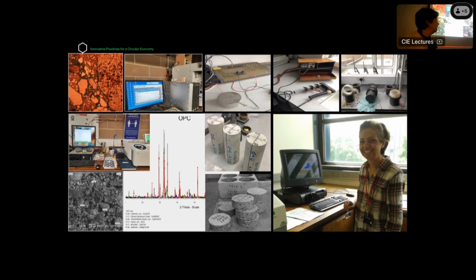Because you know that the most important thing in thermal cracking for concrete is hydration of the binder, and you can work on the binder to fix the problem. So working on that brought me to the alkali activation of pozzolanic material, which was actually a no-clinker binder, and it was geopolymer. After that, I worked on different projects at different universities to replace the cement with different materials like fly ash and slag, working on high volume fly ash concrete or using waste glass in concrete.